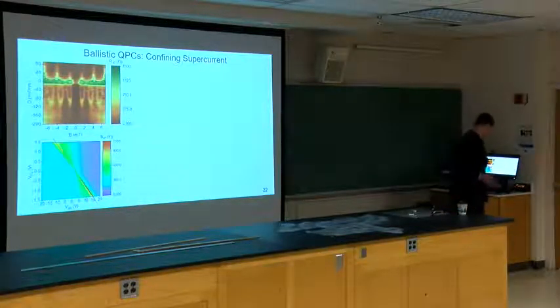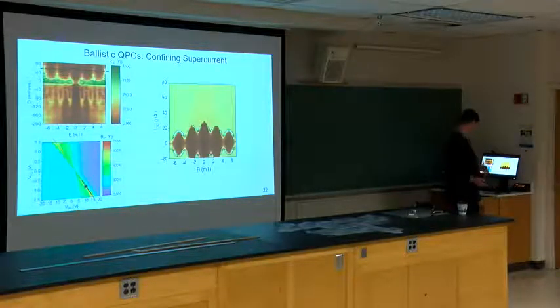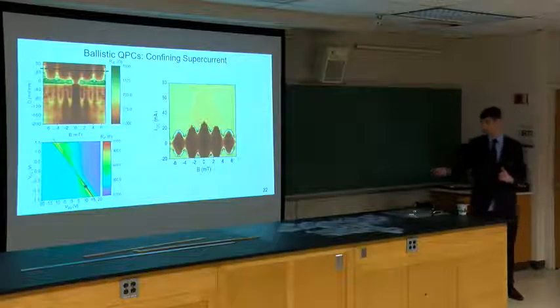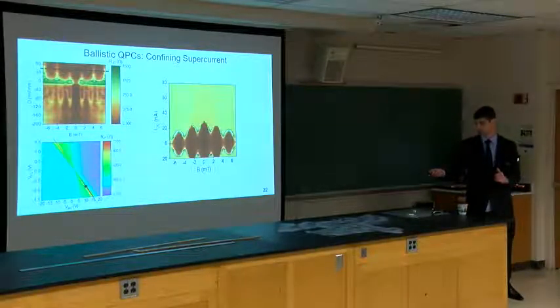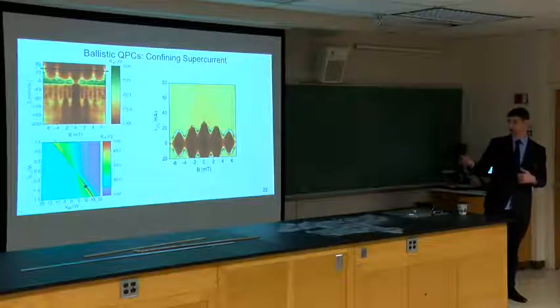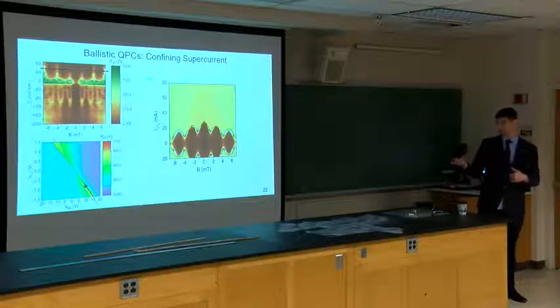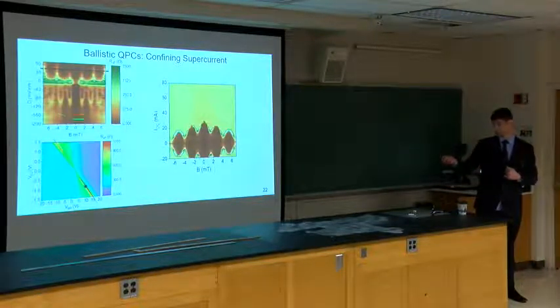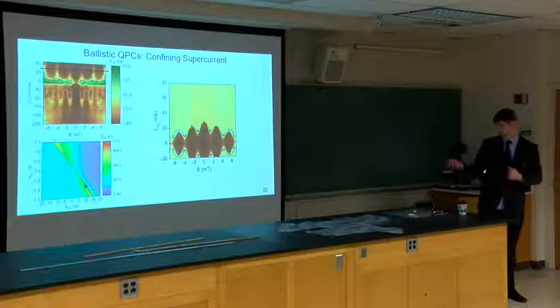So this was done at 10K. Now at 300 millikelvin, what we're doing here is we take a gate voltage, which is a certain displacement field, and we sweep the magnetic field at zero DC current, so just an AC current. The Fraunhofer pattern looks like this.